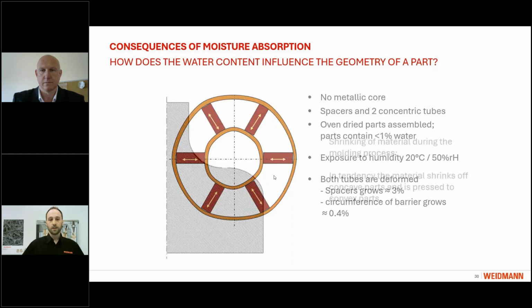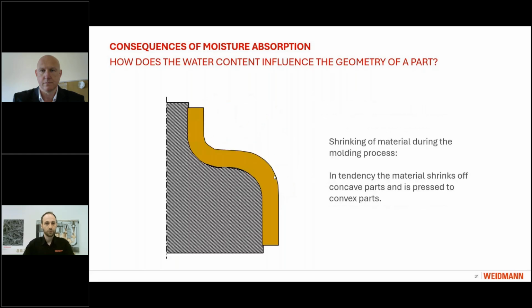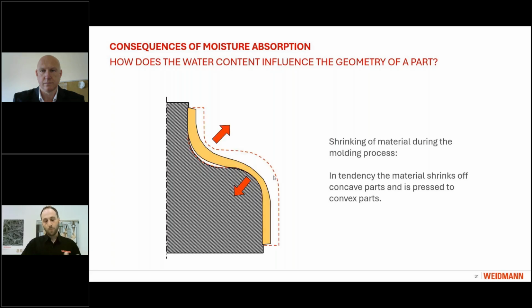When molding our material, this anisotropy of the three spatial directions shows again. When we dry this, we can see that any concave mold area will be delaminated while the material gets pressed to convex parts. So also when molding our material, be aware of this and account for it previously.